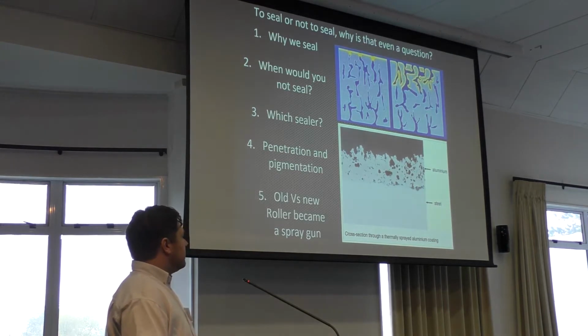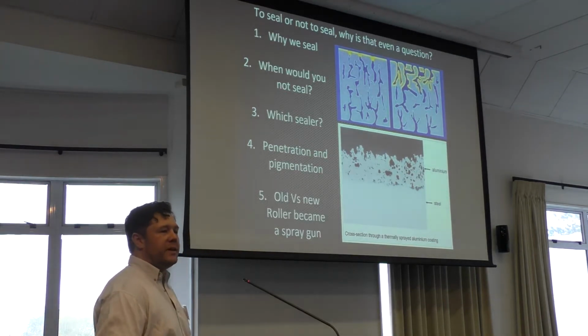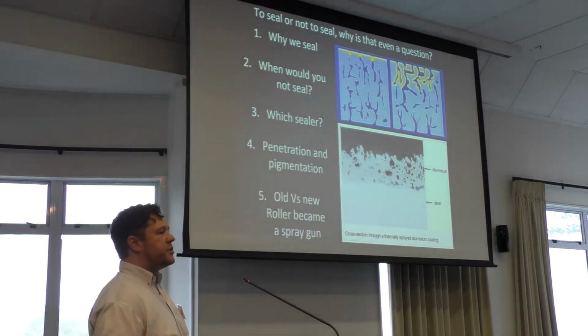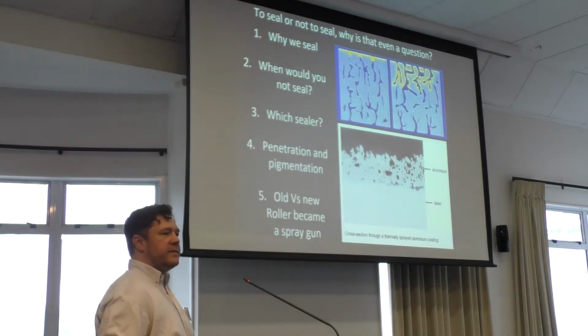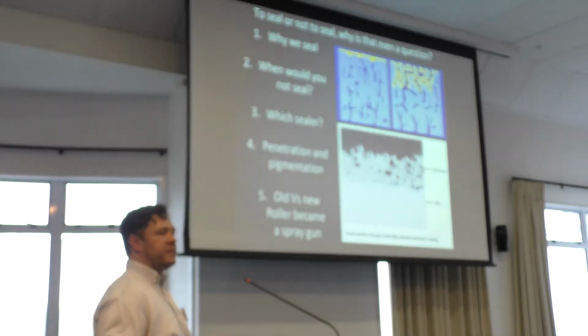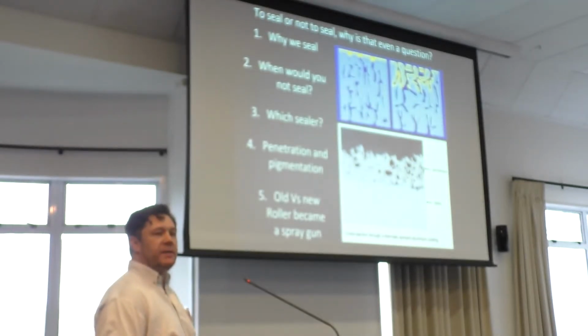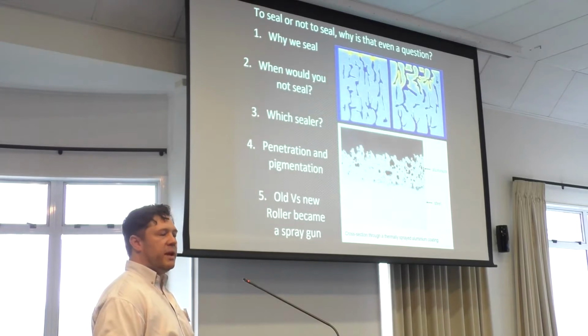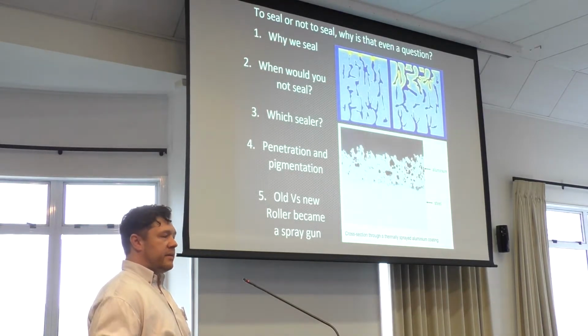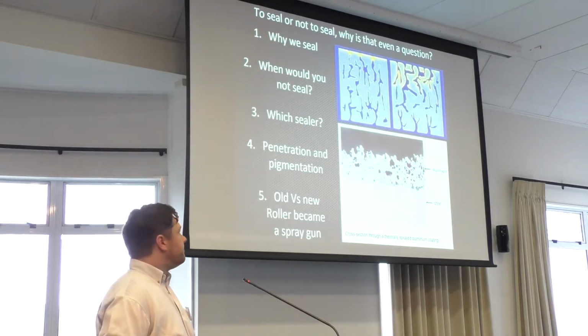So old versus new, roller became the spray gun. Back in the good old bad days when everything was applied with a roller or a brush, we were effectively forcing the sealer into the coating, which was fantastic because it helped minimise the need for the thinning of the paints, and we were still getting good penetration. But now everything's applied very quickly with a gun, so we're relying on capillary action of the paints to soak into the metal spray.